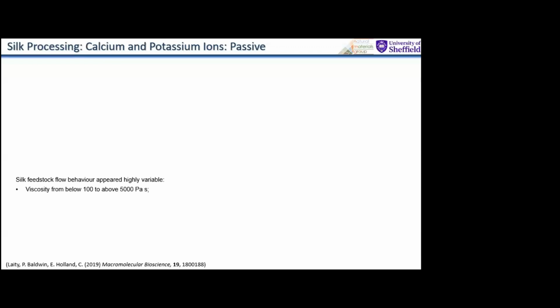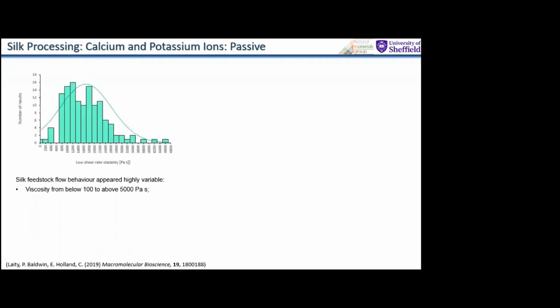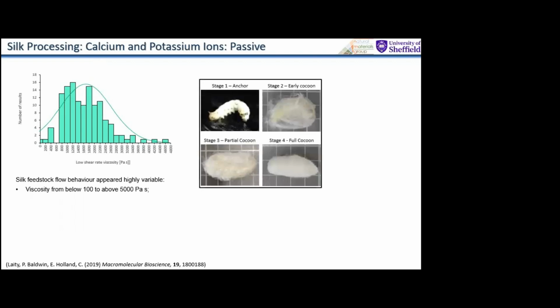And even when we got, I would say, good at it, we would still have a viscosity from 100 Pascal seconds up to 5,000, a big variation. But, you know, these proteins are exactly the same length every single time. We shouldn't get this variation. And so we started to think, well, when are we getting this silk? We always took silk from the animal when it was spun, but maybe the stage at which it was spinning a cocoon around itself would have an impact on our results.